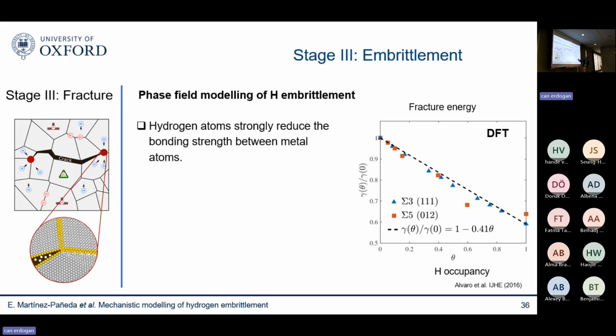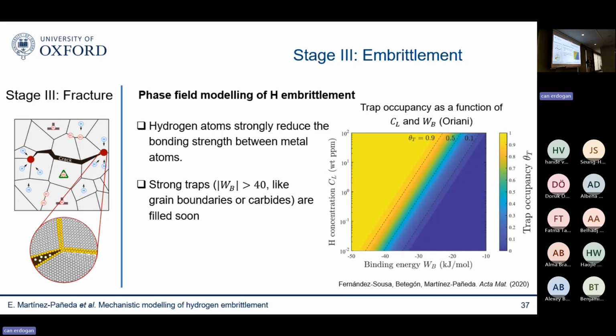But how much hydrogen is actually in my grain boundary? Because if I'm somewhere here, then this is a secondary effect. And the answer to that comes from the chemistry, the thermodynamics I mentioned before. How likely this hydrogen is to go to a certain microstructural defect depends on that binding energy, and we can measure that experimentally. And we know that for grain boundaries, which are strong traps, we have binding energies of -40 or smaller.